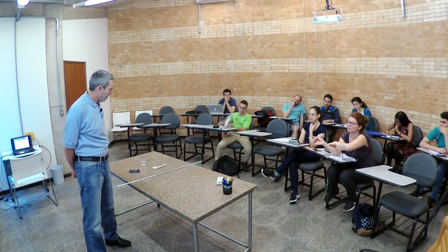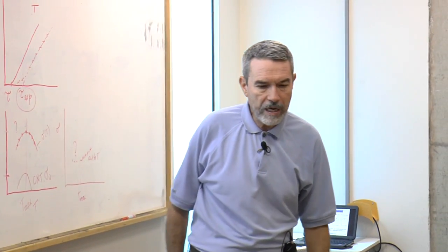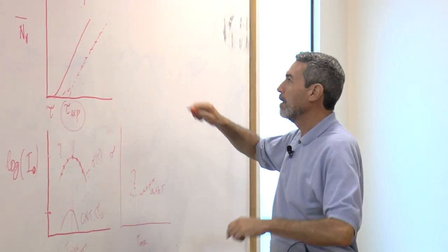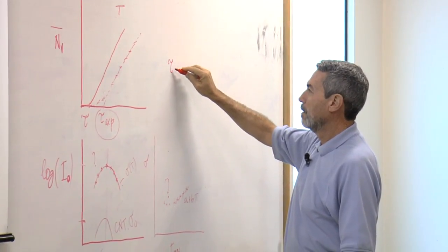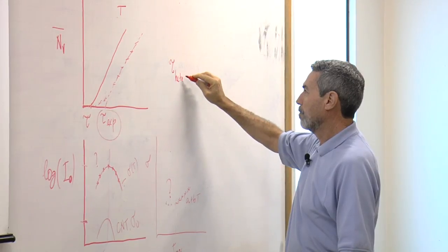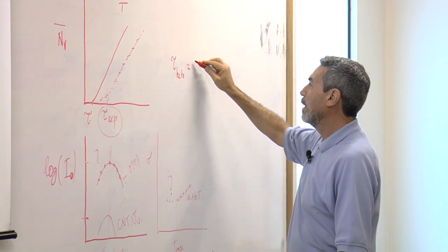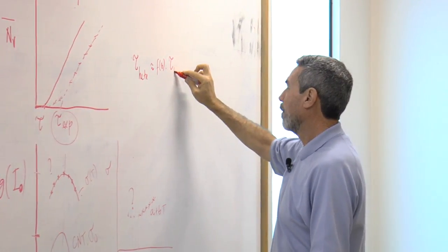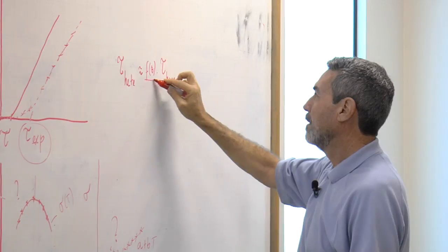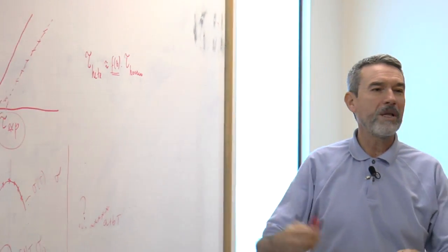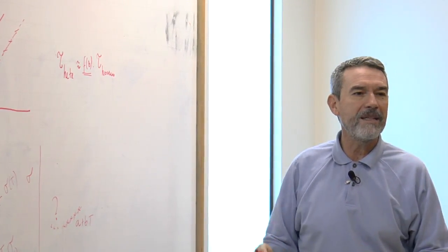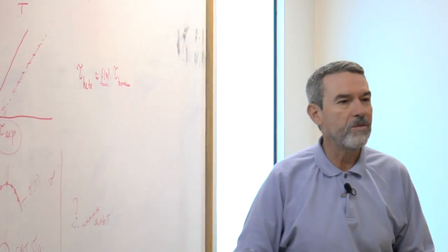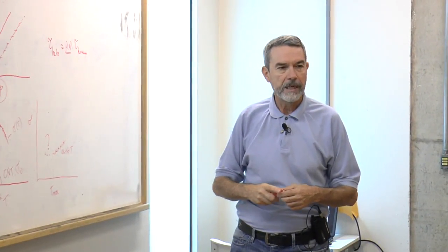Yes, because if you calculate the induction times for heterogeneous nucleation, it is only f(theta) times tau for homogeneous nucleation. This f(theta) is like 0.5, 0.3, 0.8, so it's a little bit smaller, but not an order of magnitude smaller, or 2 orders of magnitude smaller. Yeah, but it's a good question.